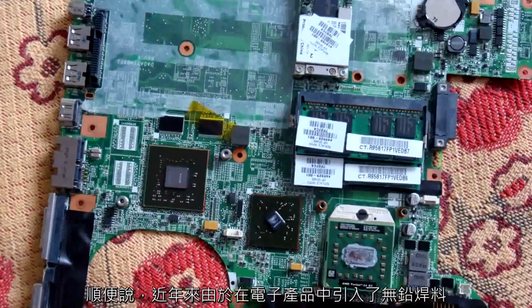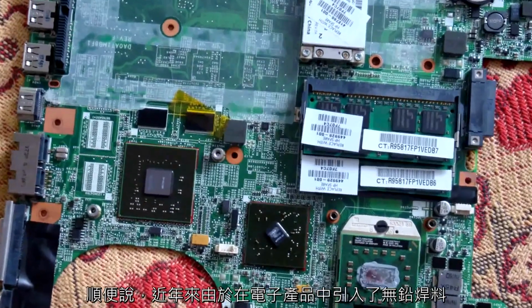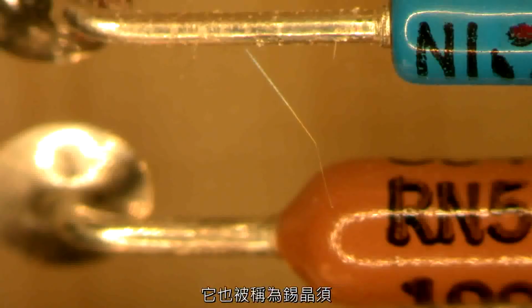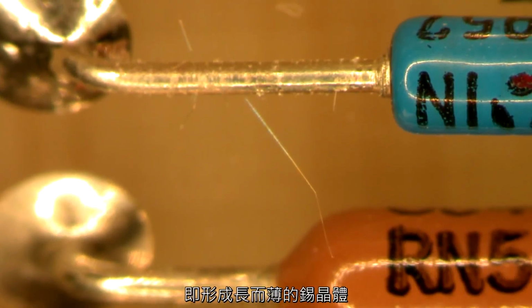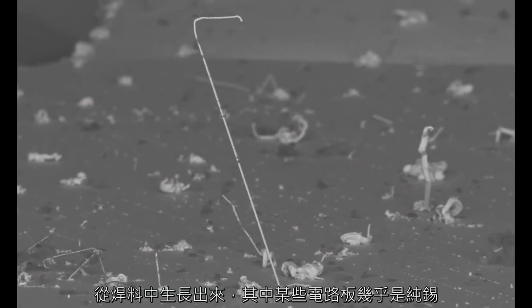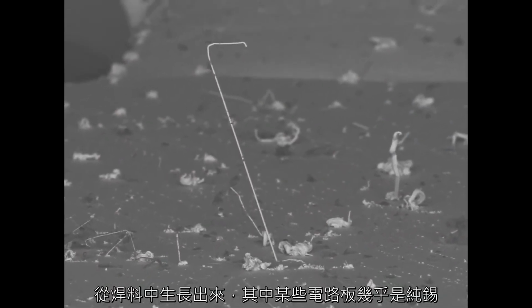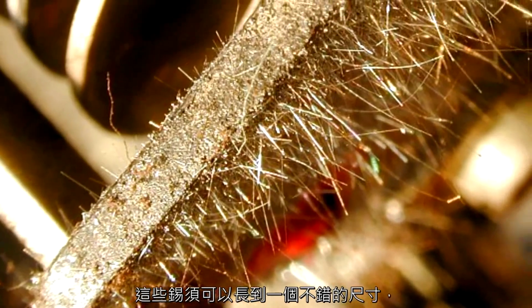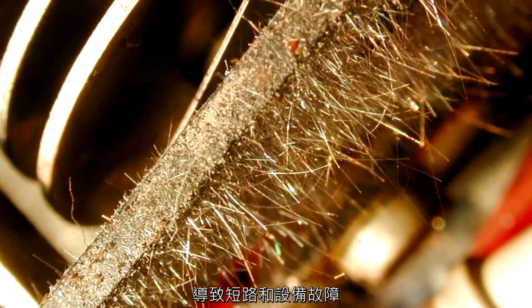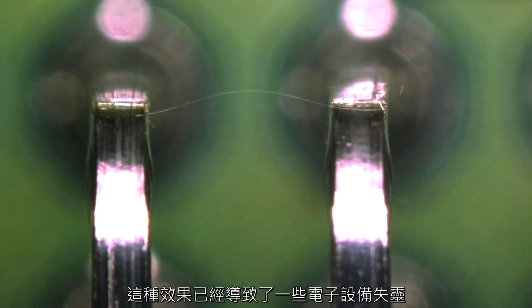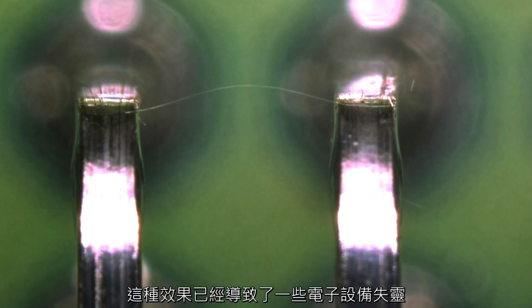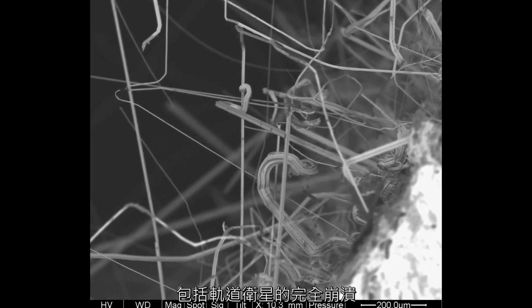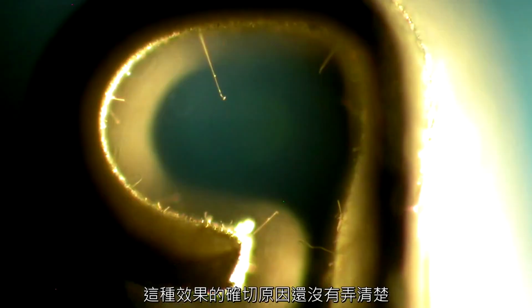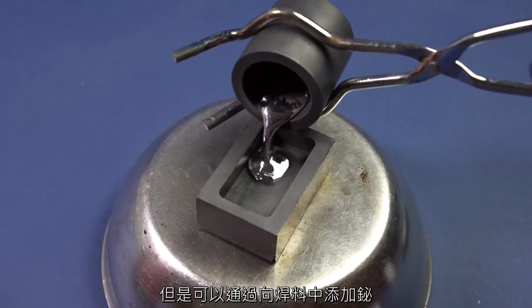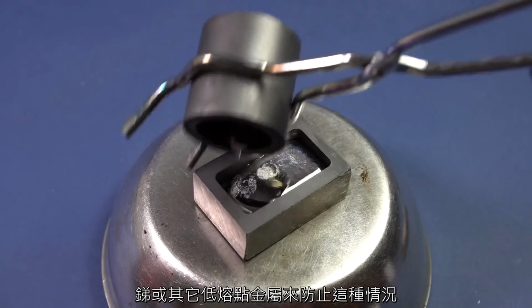By the way, in recent years, because of the introduction of lead-free solder in electronics, there is now a massive problem. It is called tin whiskers. That is the formation of long and thin tin crystals grown out of solder, which in some cases is almost pure tin. These tin whiskers can grow to a decent size, resulting in a short circuit and equipment failure. This effect has already led to a number of failures in electronics, including a complete breakdown of orbiting satellites. The exact cause of this effect has not yet been figured out. However, it can be prevented by the addition of bismuth, antimony, or other low-melting metals to the solder.